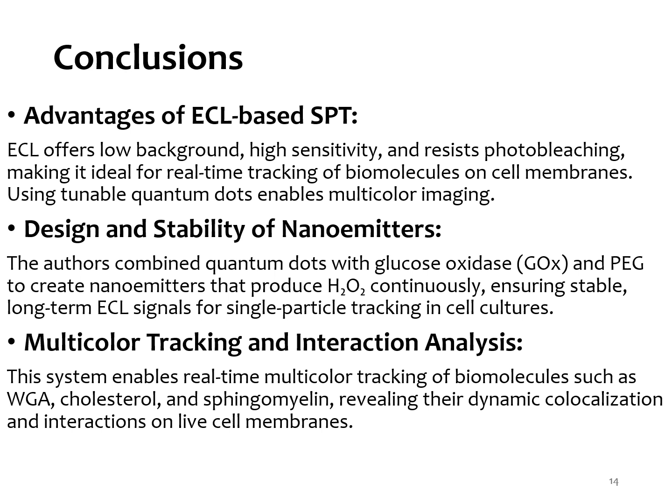Second, design and stability of nanoprobes. The authors combined quantum dots with glucose oxidase and PEG to create nanoprobes that produce hydrogen peroxide continuously, ensuring stable long-term ECL signals for single particle tracking in cell cultures.